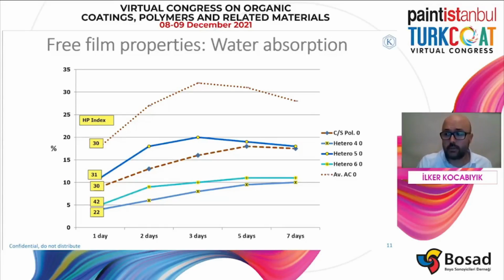As another example, the remaining lighter blue and darker blue lines represent three different heterogeneous acrylics with varying HP indexes. This is another example that a lower HP index doesn't necessarily mean lower water absorption, and it is possible to design polymers with higher water resistance by using more hydrophilic building blocks as well.